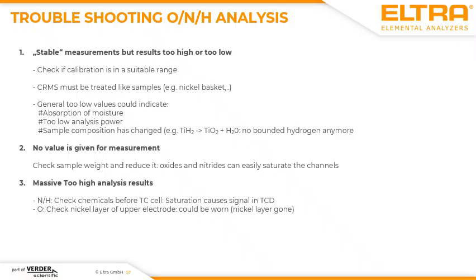When you don't get any value for your measurement, it maybe indicates on the one hand that the sample is not melted at all, or it could indicate that the sample saturates your detector, because some slags could have a very large concentration of oxygen and nitrogen. When you have, in contrast to the expected value, a massively too high nitrogen or oxygen content, you maybe have to perform some maintenance. Nitrogen and hydrogen, which are measured extremely too high, are maybe